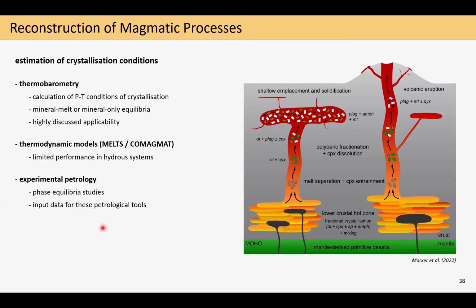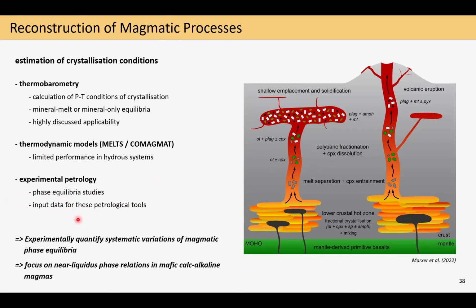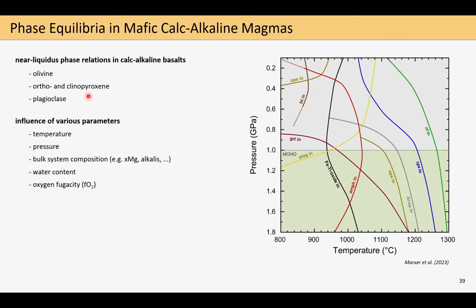So thus, in this project, we want to experimentally quantify systematic variations of magmatic phase equilibria with a focus on near liquidus phase relations in mafic calc-alkaline magmas, meaning that we were mainly interested in the stability fields of olivine, ortho- and clinopyroxene and plagioclase. We know that these are affected by various parameters, including temperature, pressure, bulk system composition, water content, or oxygen fugacity, where in this study we were mainly focusing on the first four mentioned. And the effect of pressure is, for example, nicely illustrated here in this phase diagram, where when we decompress along this arrow, we see that various different mineral stability curves are crossed.